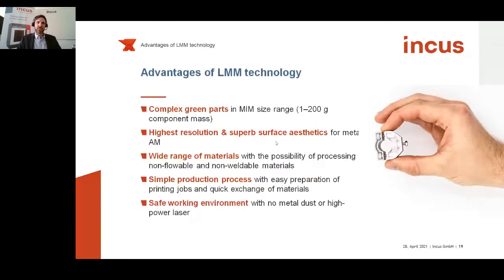To sum it up, what are the advantages of our LMM technology, our metal printing technology? Compared to other additive manufacturing technologies for metal materials, we can print parts in the highest resolution possible, also with superior surface aesthetics to any other metal additive manufacturing technology. That's what you see afterwards in the presentations as well. That's just a big benefit of lithography. Because we have a sinter-based technology, we can process the widest range of materials, because our material only needs to be available as a powder. Also, because we use this feedstock system, the material doesn't need to be flowable, so we can work with edgy powders, and this is also a benefit compared to other powder-based technologies.